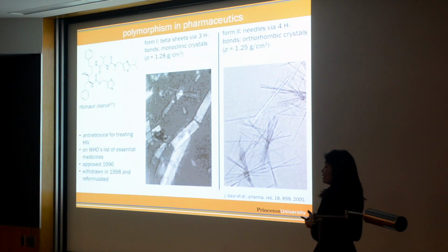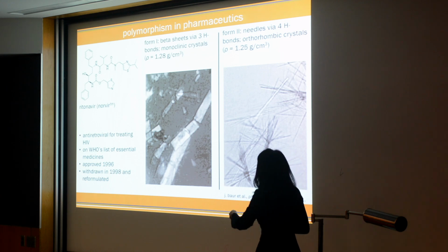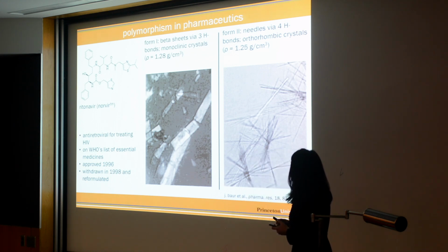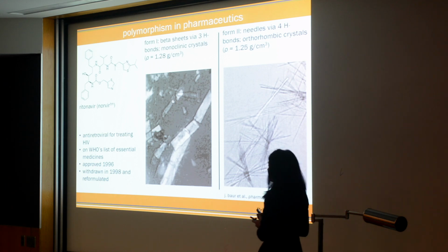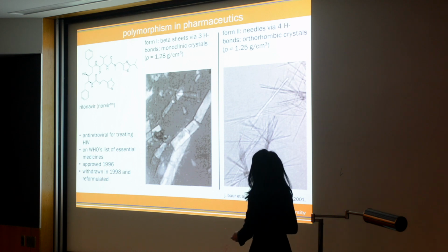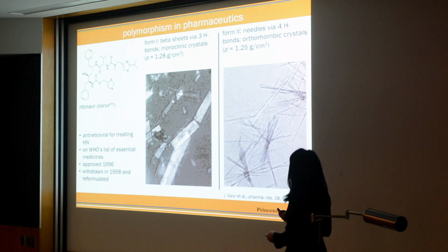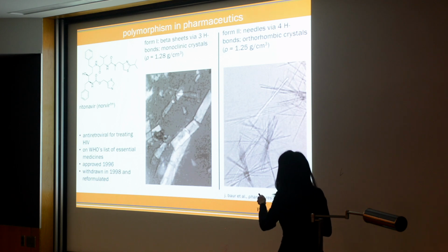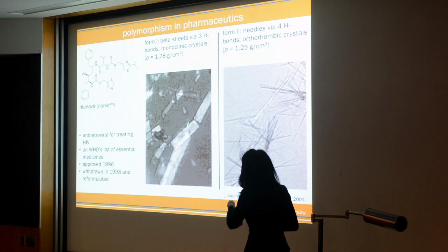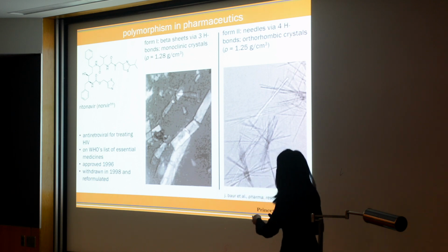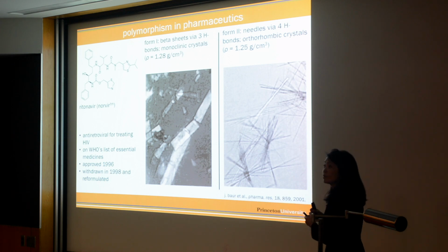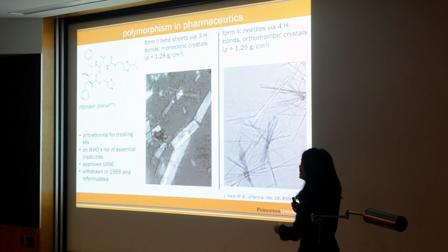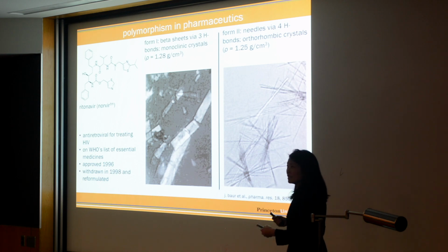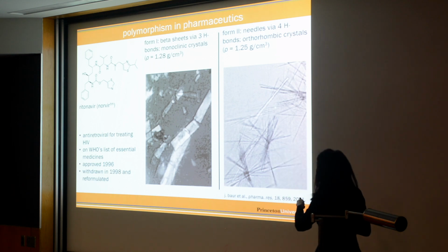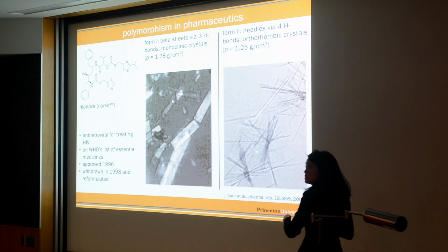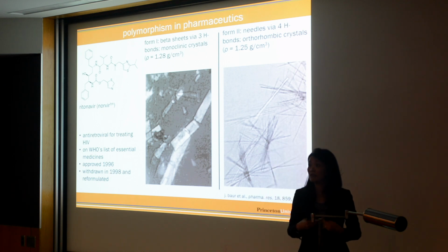This is another example that's not organic semiconductor. This is Ritonavir. It's a drug. It's an antiretroviral for treating HIV. So this was introduced and approved in 1996, but then quickly withdrawn in 1998. The bioavailable version and the soluble version is this Form 1 version. It comprises of beta sheets with hydrogen bonding. Okay? And that's shown here, the crystal habits. It turns out that as long as there are nuclei of this Form 2 present, it slowly converts to this Form 2. Never mind that Form 2 is less dense, typically associated with less thermodynamically stable. It would slowly convert to this Form 2. And as it converts to this Form 2, it becomes less bioavailable, less soluble, less effective of a drug.